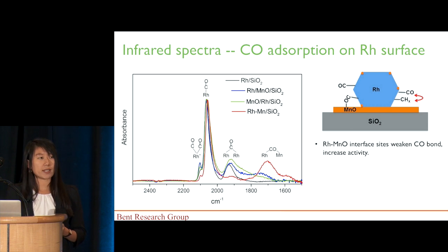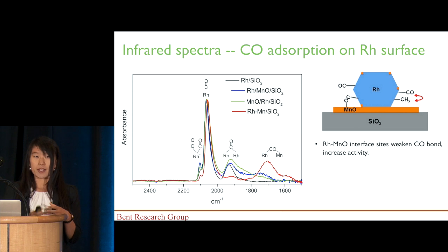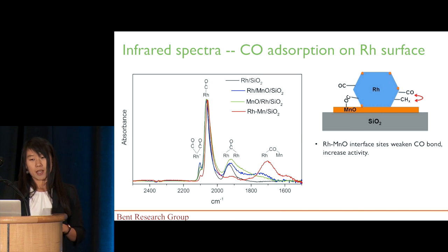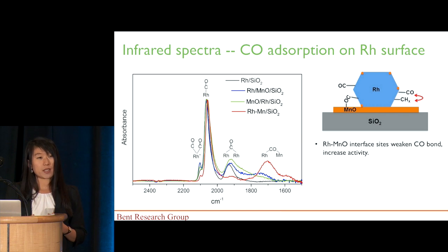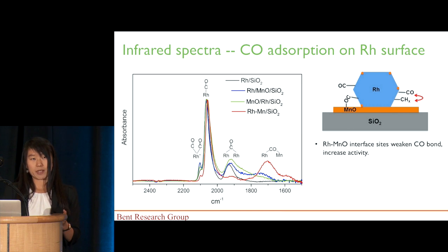For the co-impregnation catalysts, we actually saw a lot of formation of such interface sites. However, the signal from the extended rhodium surface is largely diminished. This picture agrees pretty well with the results from TEM showing much smaller nanoparticle size due to the highly intermixing between rhodium and the manganese.